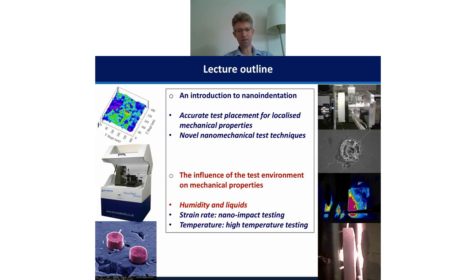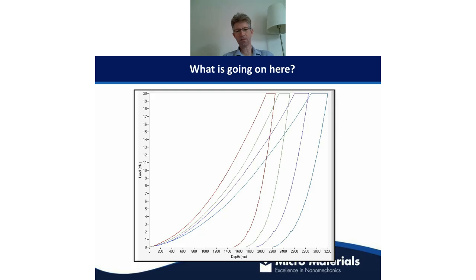Okay, so moving on now to the influence of the test environment on the mechanical properties. I'll start off by showing this graph here, and I'll say what is going on. There are 4 indentation curves. They're all different colors, and they're all on the same material, and that material is very homogeneous. If you test at different positions, you get exactly the same results. Nevertheless, we're getting this big spread in behavior. So what is going on?